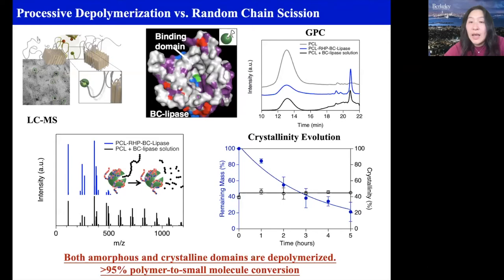And when we're looking at the crystallinity evolution, that's exactly what we see. As the process of degradation proceeds, we don't really see the crystallinity change. That means both the crystalline domain as well as the amorphous domain are being degraded. And that is important, because otherwise you're going to leave the highly crystalline domain behind.